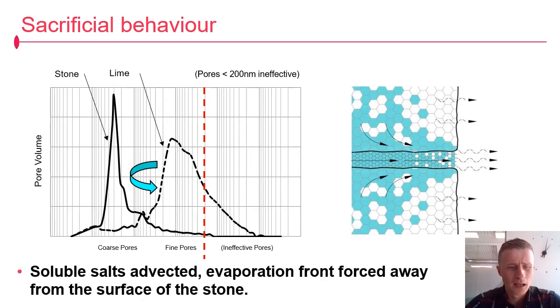How does this work? Okay, so when you've got two porous materials of distinctly different pore size in intimate contact with one another and chuck a bucket of water on that, you have a poultice. So water is preferentially drawn out of coarse pores into fine pores by those same capillary mechanics we've seen earlier on. And with the moving water come the soluble salts, and this is mobilised by wetting and drying cycles, and we get those several times a day on the west coast of Scotland. And over the lengthy lifetimes of masonry structures, you get an incredibly pronounced salt management process.